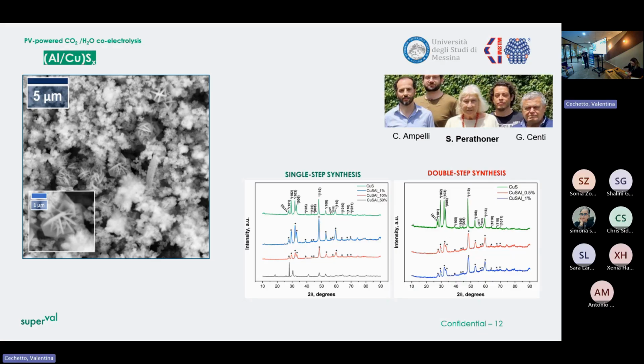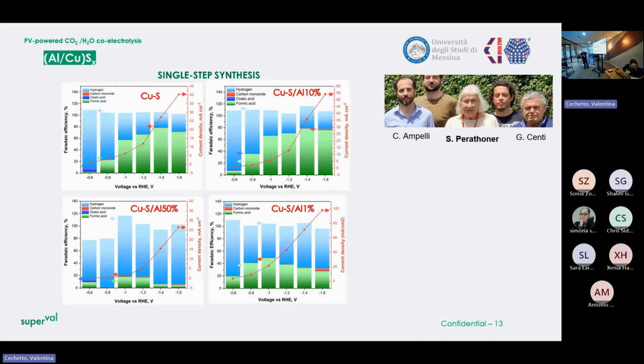So the idea of Messina's team is to use variations of copper sulfide. They have been preparing different syntheses of this material with different aluminum incorporation into the mixture. And here you have some preliminary data that they have achieved for this task. You can see that depending on the potentials, these kinds of materials get potential windows where the formate to hydrogen ratio is about 2:1, which is something that we are expecting. And you can see that the CO production is almost negligible, below 0.1%. That was part of the challenge.